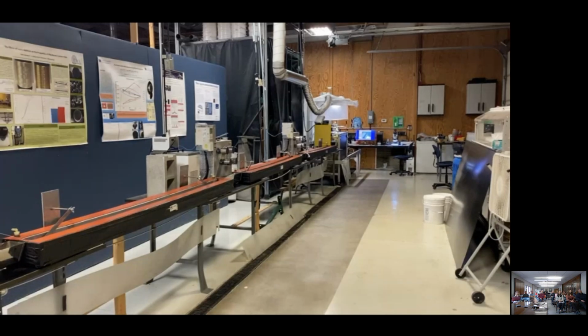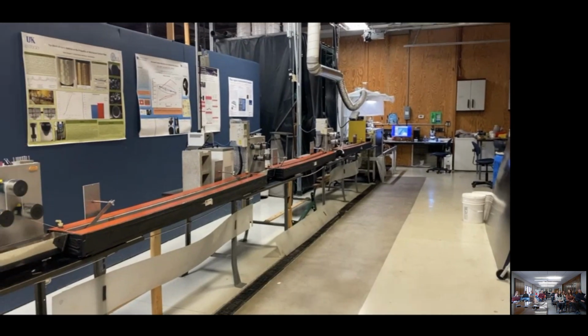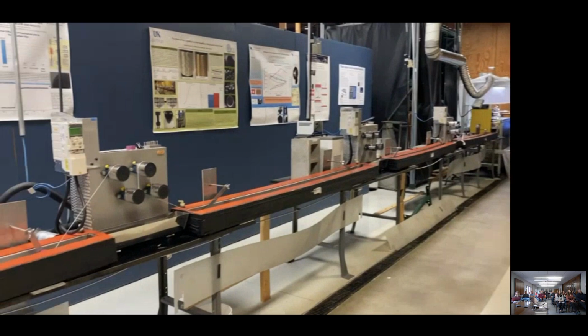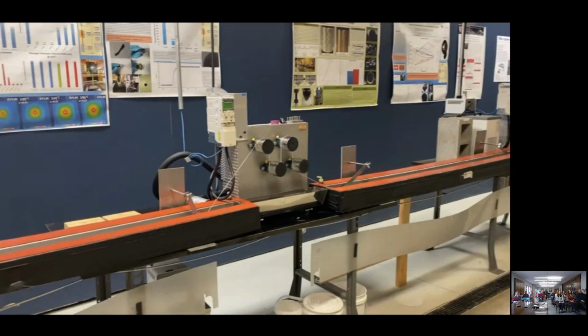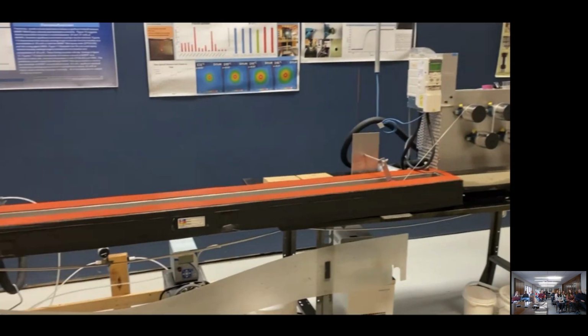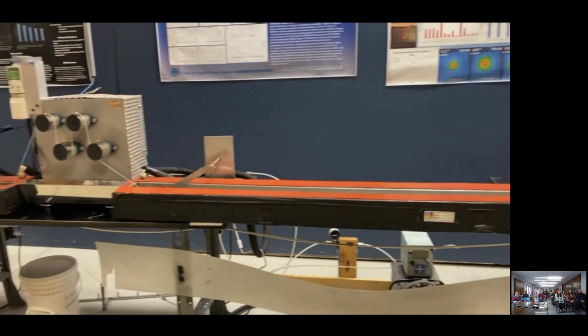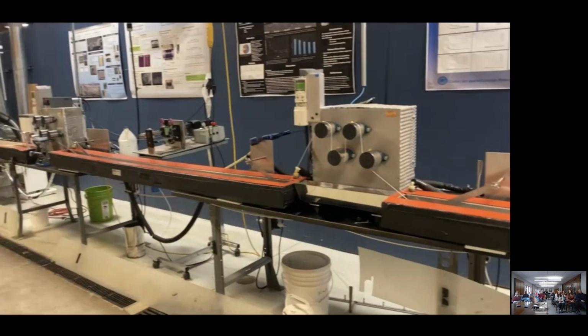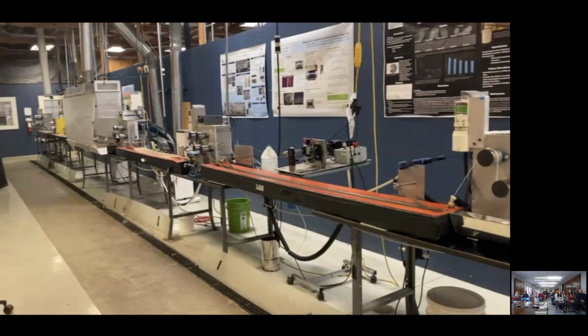We're doing 100. After that, the tow makes its way down the line through water baths, which wash the fiber of any residual solvent trapped within the porosity of the nascent filaments. Then down at the end here, we're going to do some higher temperature stretching.